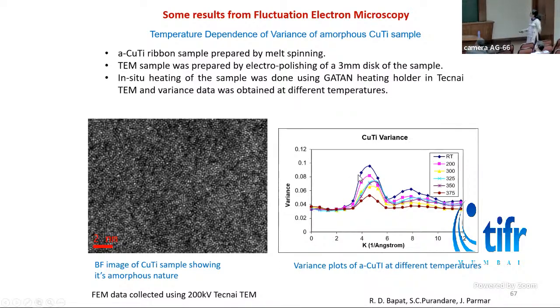Here we could see that at room temperature, the variance is very high. That means it had medium range order. And as we heated the sample, we can see the medium range order disappearing. This work is still in progress.